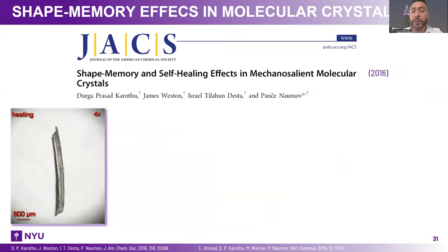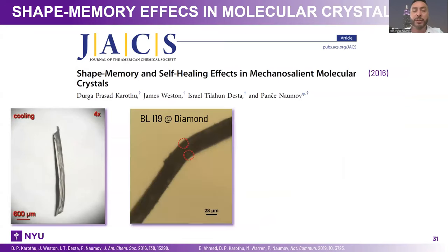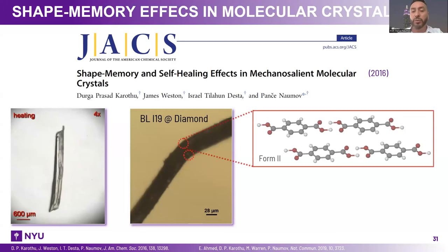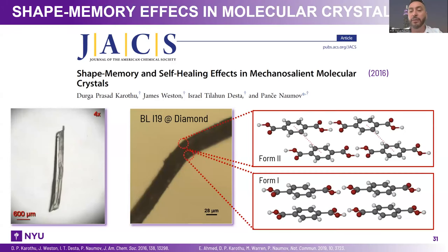And in 2016, we published the first shape memory organic crystal. So what is happening here is when you push the crystal, you actually induce a phase transition in only part of it, but the other part remains as it is. And we have evidence for this because we used single crystal X-ray diffraction, a microfocus X-ray diffraction, to determine the structure of the two parts. And we see two different phases. So basically we have one form in one half and the other form in the other half. And then when we heat the compound, the second form goes back to the first form. And so we have this effect of mechanical memory, which is in some far analogy similar to what we observe in metals and metal alloys.